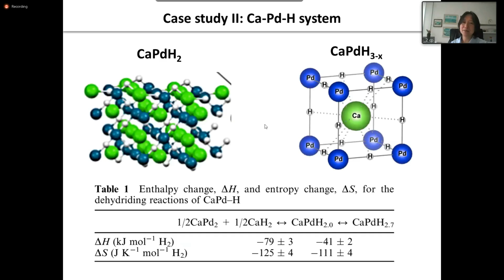And then I'd like to move on to the calcium palladium hydrogen system. For this system, I'm not going to talk about nitrogen fixation, but I'd like to talk about hydrogen content at the surface of the complex hydride. For this calcium palladium system, the most stable state is CaPdH2. And we also have PdH2 units in the lattice. There's another structure, with hydrogen content more than 2.